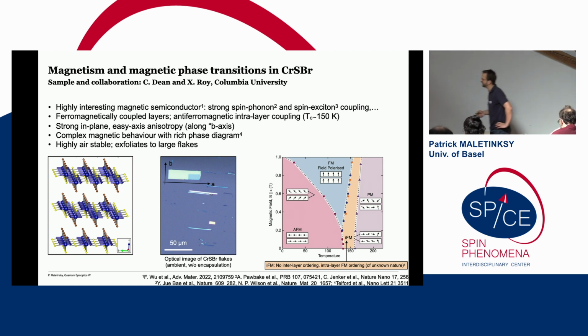And then lastly, I want to say that this material has an interesting and still not fully understood phase diagram. So this is sort of a rough sketch of magnetism in chromium sulfur bromide as a function of temperature and magnetic field. You have various transitions, for instance, metamagnetic transitions, where you can drive this into a ferromagnetic order, but also this rather interesting intermediate phase here that happens roughly at 150 Kelvin, where it turns out that neighboring layers become uncorrelated, but you maintain ferromagnetic order within each layer. At the same time, you're losing anisotropy. So this is something that could mimic possibly an XY magnet, but that remains to be seen.